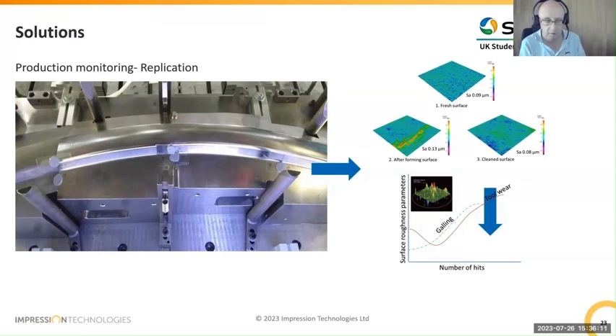They're like little ball bearings, but they're adhered quite strongly to the surface of the tool. And if we dissolve those with a caustic soda solution, then we get back down to the original metal and also the original surface finish of the metal. Whereas if we were to try and abrade those off, then we would be changing the surface finish of the tool itself, which could lead to galling coming on at a much more rapid rate. And in addition, if we've got a PVD coating on there, then we would be removing it within a few short runs and having to send the tool back for another expensive recoat.